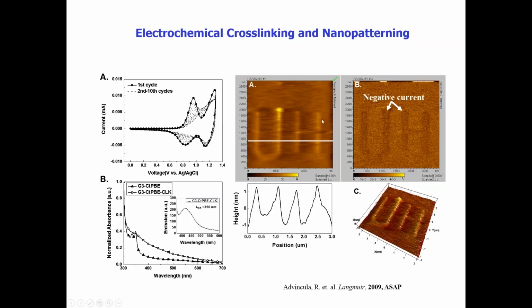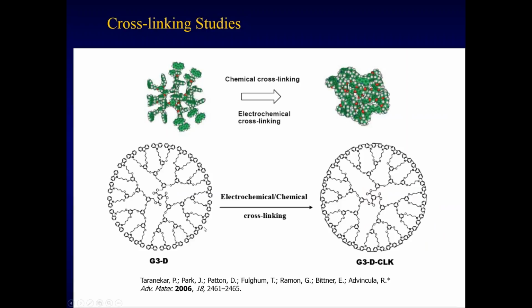What we have here is a flat ITO substrate or a doped silicon surface where we have the dendrimers placed from a very dilute solution on the surface, and then we applied a current by rastering over the image, and we observed that the height increased, as shown here, after we applied a bias voltage along the surface. And then we remeasured the height. We observed that the height increased as we did this